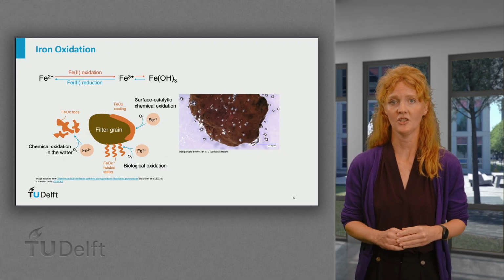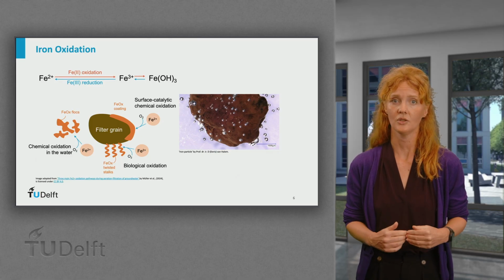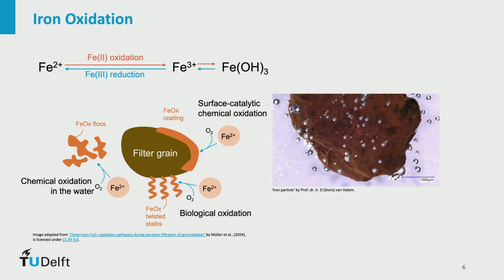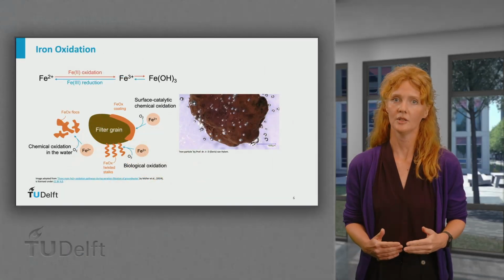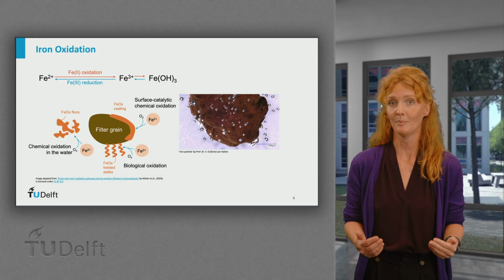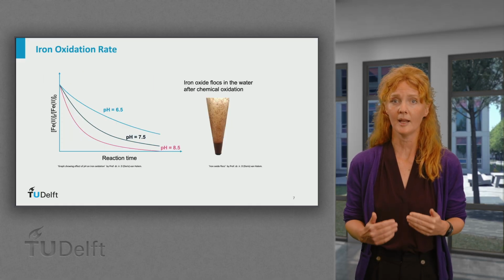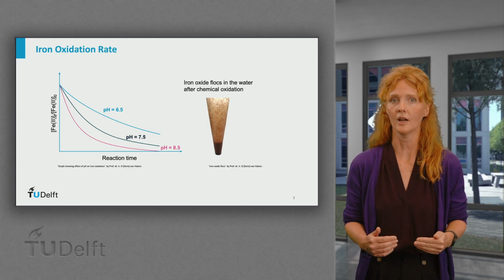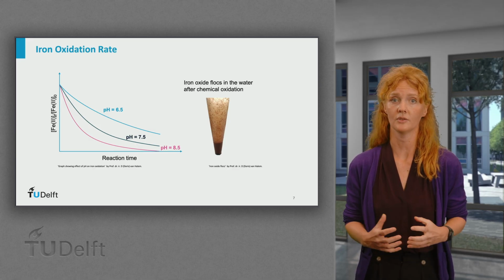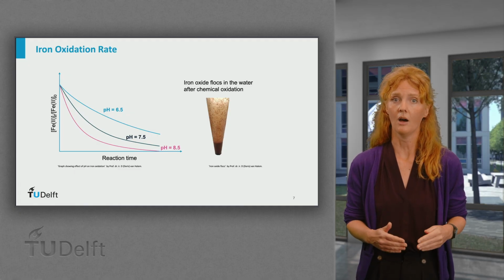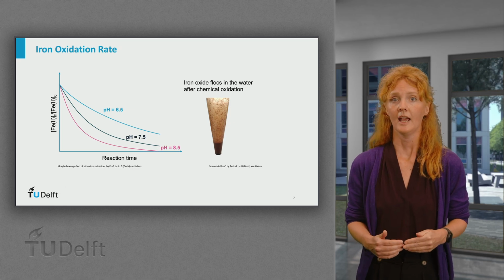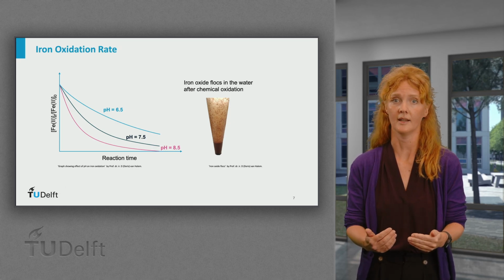While we know that ammonium oxidation is a biological process in filters, iron oxidation can occur both chemically and biologically. In anaerobic groundwater, iron occurs as ferrous iron, or iron 2+, which is a dissolved, reduced iron species. Chemical oxidation can occur in the water phase, as well as surface catalytic on the sand grain surface. Biological oxidation will only occur on the sand grain, as this is where the biofilm is hosted. The rate of chemical iron oxidation to iron 3+ or ferric iron depends strongly on pH and oxygen concentration of the water. After aeration, oxygen concentration tends to be close to saturation, and the pH has increased due to the flush out of carbon dioxide.